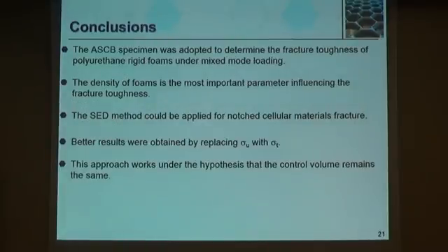To conclude, we used the asymmetric semicircular bend specimen to determine the fracture toughness of these polyurethane rigid foams. As expected, the density of the foam is the most important parameter influencing the fracture toughness.